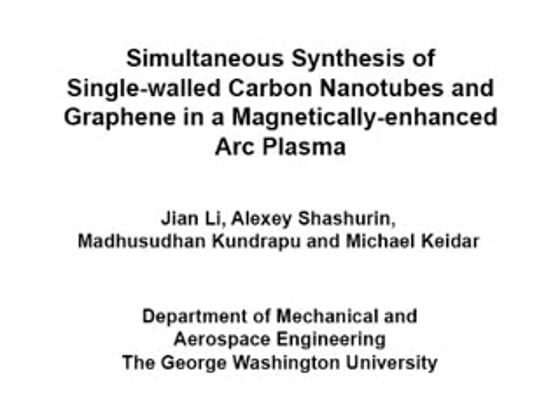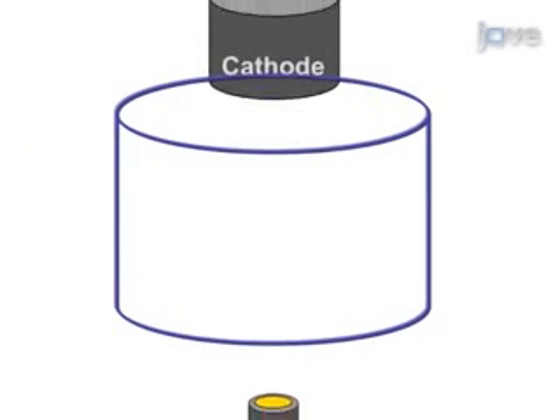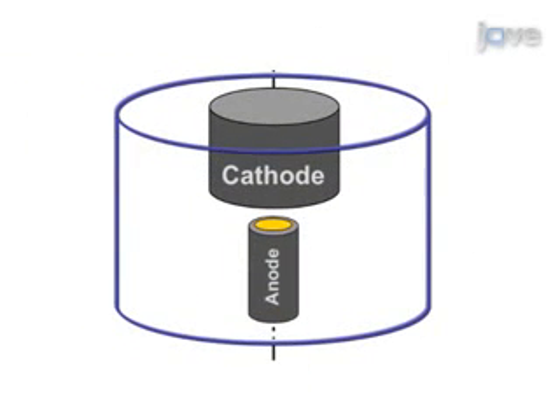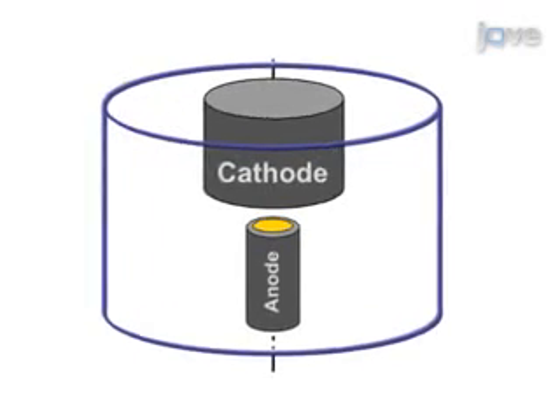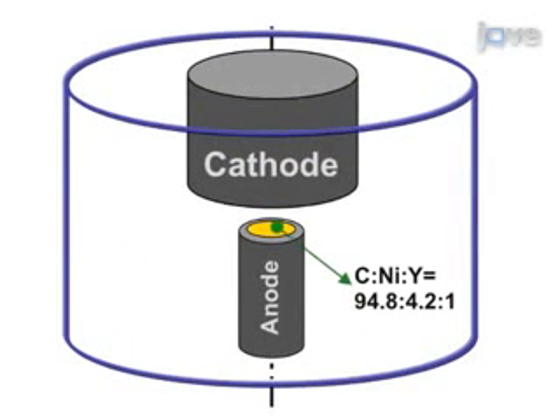The overall goal of the following experiment is to synthesize single-walled carbon nanotubes and graphene in arc simultaneously. This is achieved by first preparing two arc electrodes, anode and cathode. The anode is fabricated with a specific ratio of carbon, nickel, and yttrium of 94.8 to 4.2 to 1, and the cathode is a pure carbon rod.